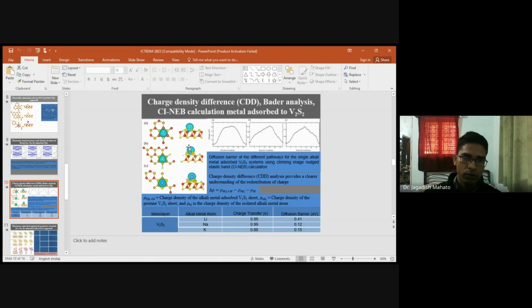The figure on the left hand side shows the isosurface plot. From that we can see that the metal atom really gives enough electrons to the sheet, and from the Bader analysis we can quantitatively calculate the amount of electron transferred from the absorbed metal to the sheet, which is tabulated here as well. Then we calculate the diffusion energy barrier, and we found that for the lithium atom there is a very small barrier. For lithium atom it is 0.41 electron volt. For sodium it is 0.12 electron volt, and for potassium it is 0.15 electron volt using CI-NEB calculation.